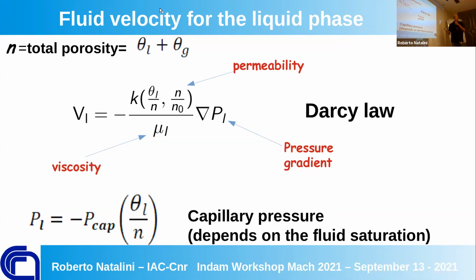And so these two terms are crucial. They are characteristic of the material on one side, but also of the liquid you are using. Right? For instance, you have no water, but you have, I don't know, white spirit, because you are introducing some consolidant, as you will see later. And so it's a mixture of white spirit and water entering inside of the pore. So this relation can change. But essentially this part is the liquid, and this part is due to the geometry of the material, the so-called permeability, which can be a matrix. Here we are assuming a scalar, but it's much more complicated than that.